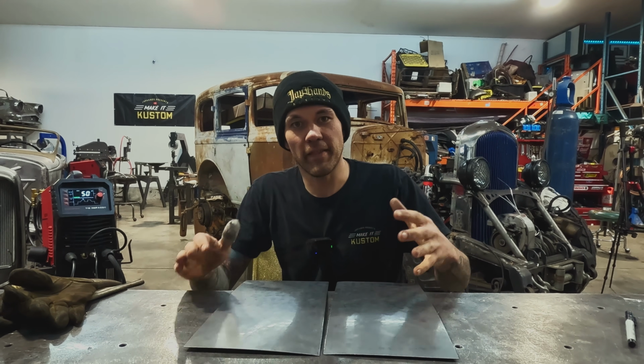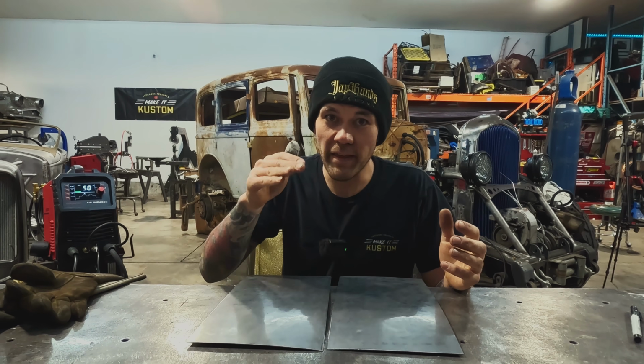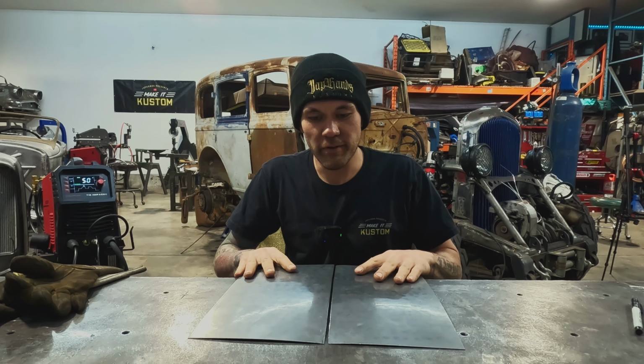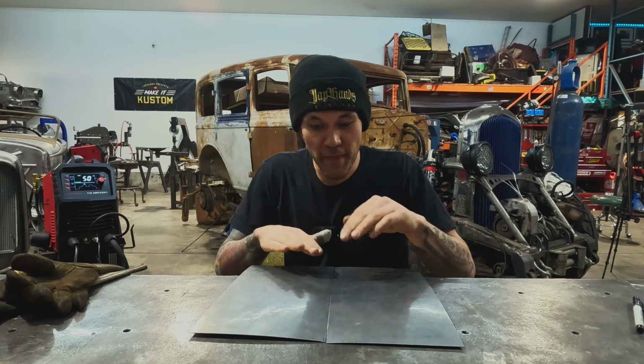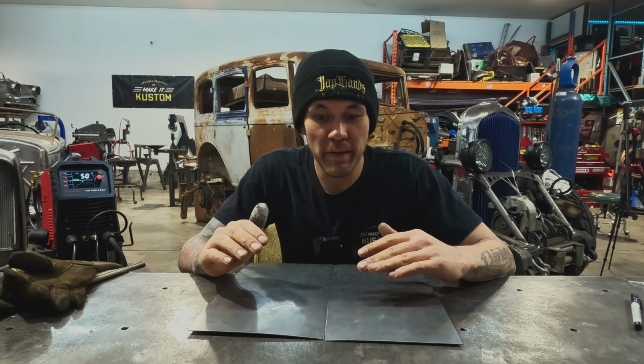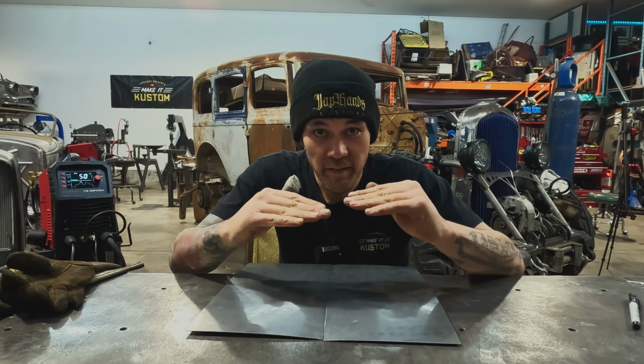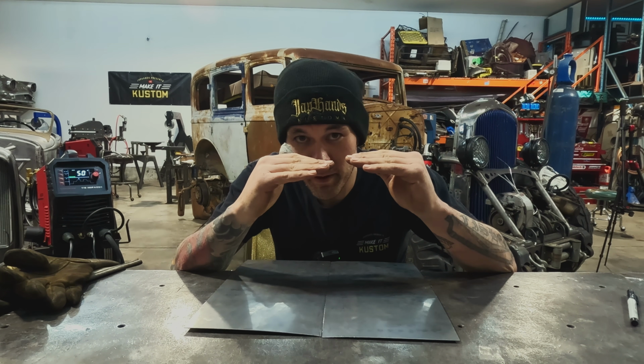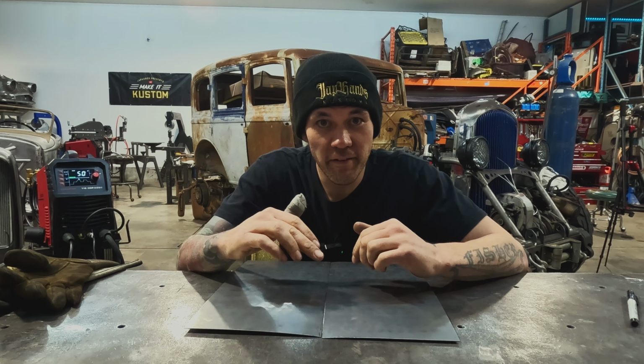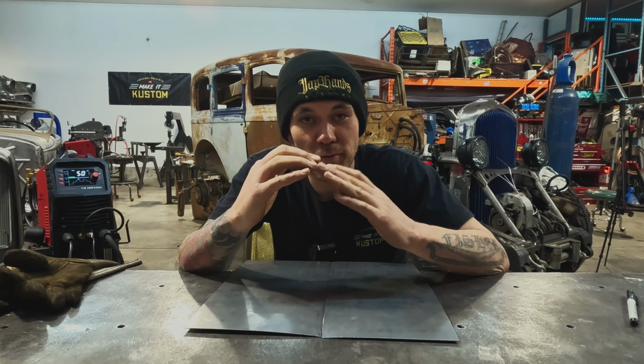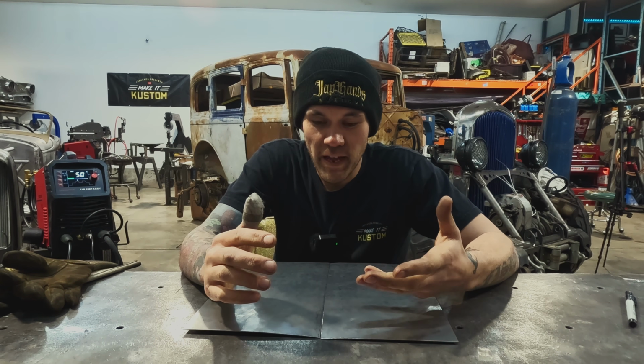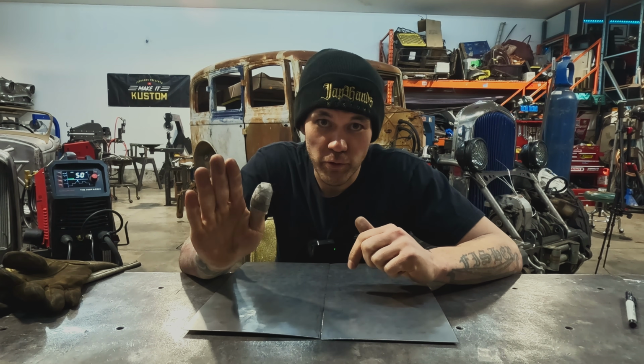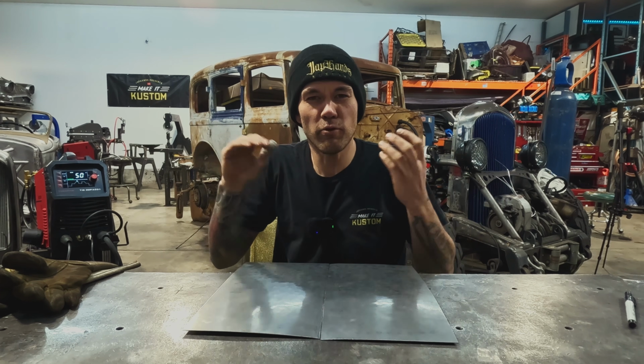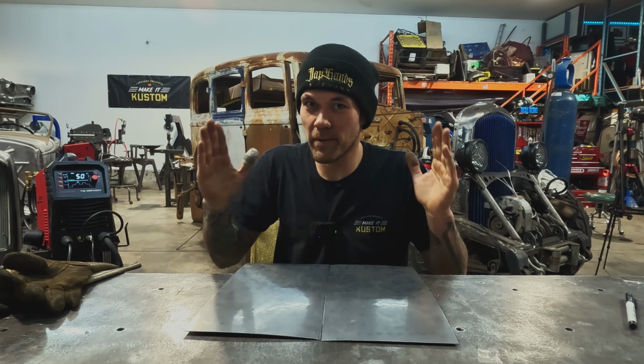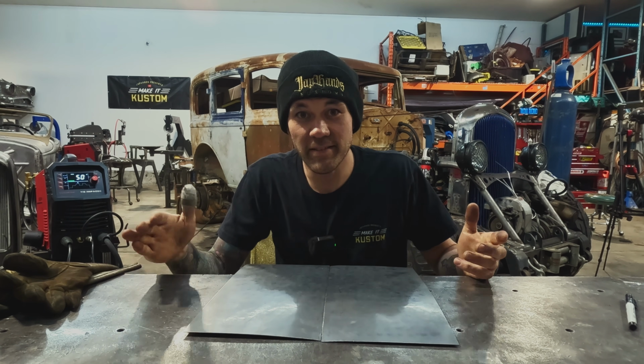Once you've got a joint that is fitting super tight, the next thing is the way that you tack that piece in. If I tack this piece right now on this end, and then try to fit the middle, I've already screwed it up. Because if I tack on this end and that end, and one panel is slightly above and one slightly below, by the time I tack those all together, it's going to bunch up, and one's going to be too low and one's going to be too high. So what you must do when you're tacking is you start at one place and you just work from there. That's why all your fitting has to be so good. If you can trust your fitting, like it only fits this one way because it's so tight of a fit, then you know that if you can get that panel in there, it's going to fit that way.